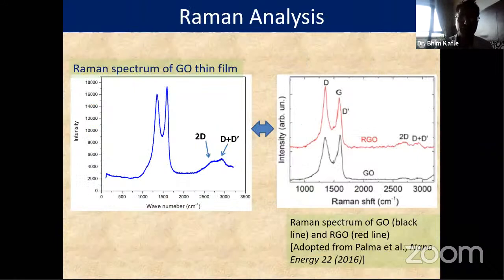And also you can compare this Raman peak of our sample with the published one. If you compare here, the appearance of this 2D peak and D plus D peak confirms that the positions of these two peaks are very close to other groups' work. Here they are not resolved very nicely, but you can see the signature. It confirms that we became able to form GO or semi-RGO.